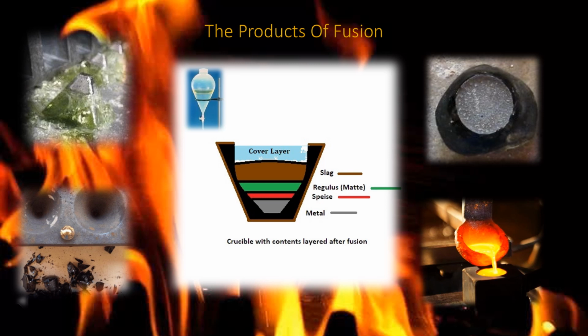The next layer, if present, will be matte. Matte is also an unwanted layer. It is an artificial sulfide of metals. It is usually found during a niter fusion of sulfide ore. It forms when the charge is too acidic. It will show up as a blue-gray brittle layer lying just above the lead button. Depending upon the amount of matte formed, it may be a considerably thick layer, or it may be just a granular coating sitting on top of the lead button. Gold and silver are soluble in matte. The result is gold and silver losses, as the lead globules produced during fusion will not collect all of the precious metal due to the formation of the matte constituents.